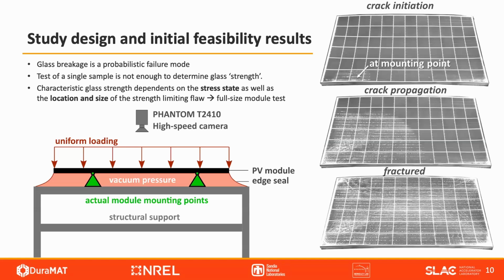So we came up with the study design here, and we did some initial feasibility results where we built like the static mechanical load test setup. This black bar here is the PV module. We apply uniform load. It's mounted on the actual mounting positions, and we put a high-speed camera on top. So the idea was to figure out, okay, what is the fracture load? And we also wanted to figure out where the glass is breaking from. And so those are images from the high-speed camera, and you can see, okay, crack initiation started here. You can actually see the crack front here with the fracture pattern. And then this is the completely damaged module.